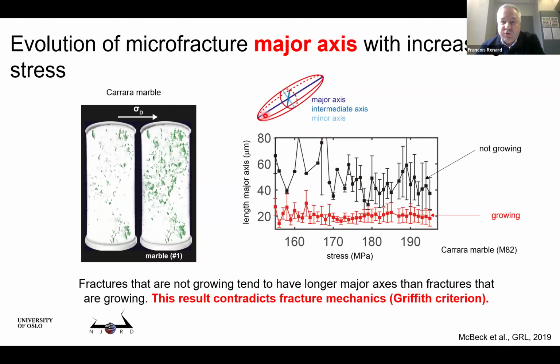So this one is the length of a fracture, so the longest axis. The black ones are the fractures that are not growing. They have a length of around 40 micrometers. And the fractures that are growing are the fractures that have a smaller length. For those who have studied fracture mechanics, it's the opposite of fracture mechanics. If a fracture is longer, it will grow more. It will be easier to grow than if it is shorter. So more or less, this result contradicts fracture mechanics and the Griffith criteria, at least at this scale.